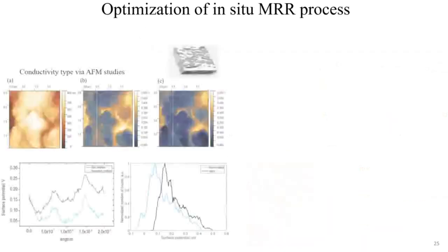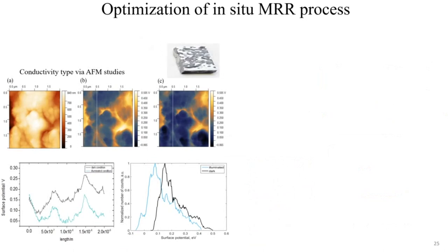Also, an attempt to understand the doping type of this nanostructured silicon coating was made using conductivity measurements with EFM, where the surface potentials of the coating were studied. And we know that surface potential is related to the work function of semiconductors, and this is quite different for N-type and P-type semiconductors. So our finding from this was that the most likely conductivity type of the nanostructured silicon coating was N-type, and the conductivity type could have come from the substrate, which was N-type.